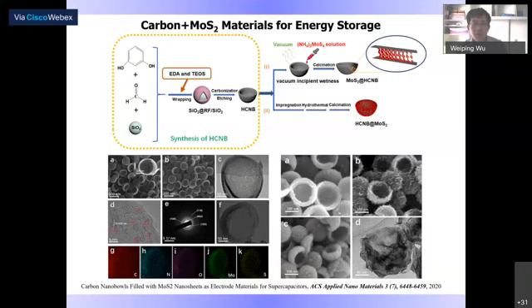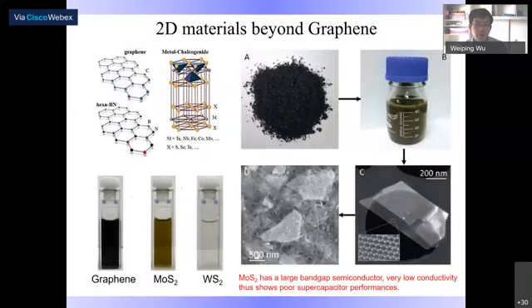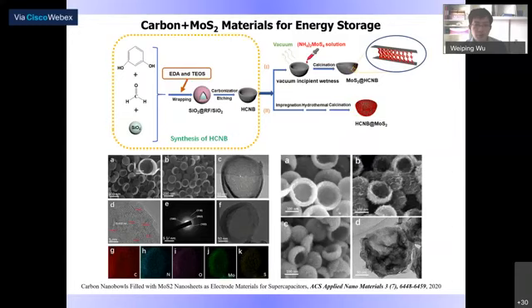One is the MoS2 inside this carbon nanoball. And the second type is MoS2 coated on the outside of this carbon nanoball. As you can see from the SEM imaging and the TEM imaging here, the material we obtained is exactly the same as the structure we intended to design.